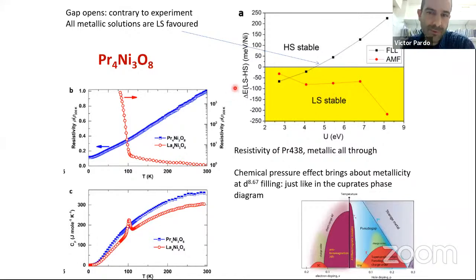So what we did was comparing the energy of the low spin and high spin with two different LDA plus U flavors. This introduces correlations in the d band, something similar to what you do with the Hubbard model. And there are different ways that you can introduce correlations. They are called flavors in the LDA plus U method. So we used two of them. And what we saw is that this flavor called AMF gives that the system is low spin for all values of U. In the past, we knew that also for lanthanum 4 nickel 3 O 8, this particular flavor of the LDA plus U was giving a better agreement with experiments.